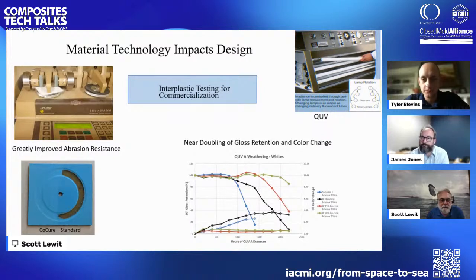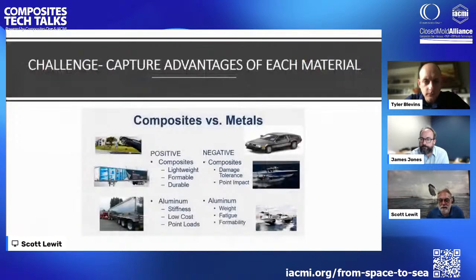The more urethane you put in, the better the stuff gets. This is CoCure 15, and you can see in abrasion it's about double. If I go to CoCure 50, it's 10 times the abrasion resistance of gel coat. 10 times.